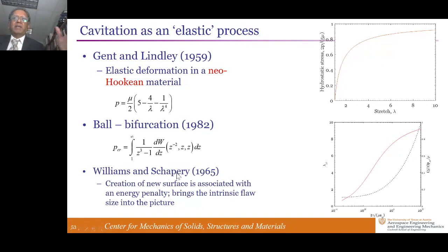Max Williams, my academic grandfather, had a different idea where he introduced the idea that fracture energy on the surface must be accounted for, but he still worked on this within the framework of a neo-Hookean material. And so the neo-Hookean instability still was at the limiting part of this picture of fracture. The basic question is: is this cavitation and its growth a deformation problem leading from instability, or is it a fracture problem leading from surface growth? So new experiments, new diagnostics are needed in order to accomplish this.